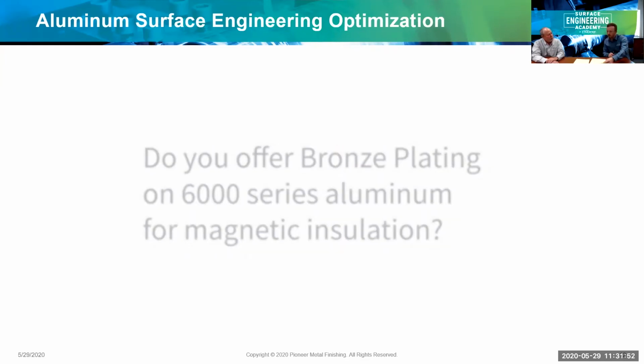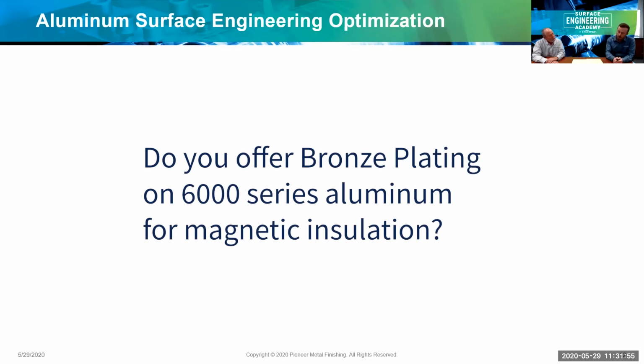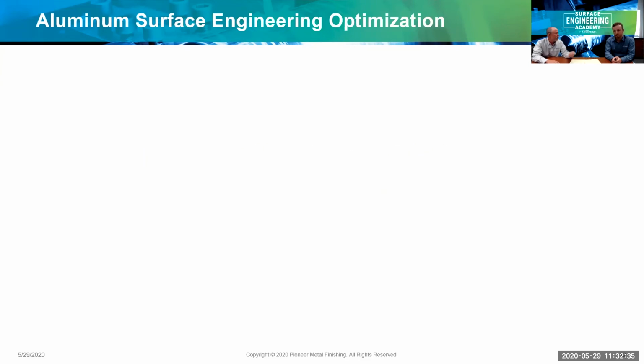Next question. Do you offer bronze plating on 6000 series aluminum? If so, would it need to have a diffusion layer? Parts for an MRI environment where plating layers such as nickel are not allowed because of magnetic properties. So the bronze being somewhat of a magnetic insulation. Yeah, we don't offer bronze plating, but as far as magnetic insulation, we do offer the electroless nickel, the high phos electroless nickel for our Norgard. That's a non-magnetic coating. I don't know if that would meet this requirement. Looks like Jason wrote into us. We'll have to get back to you on that, Jason.